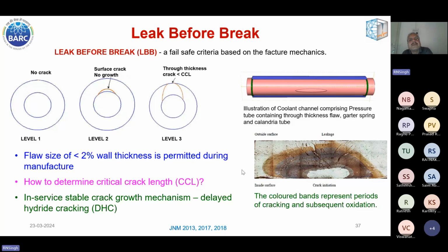No, this crack is just a schematic to show that it is breaching the wall thickness. Usually these DHC cracks are very sharp. It is almost like a sharp planar crack. It is not a volumetric flaw. And for this, I think the actual flaw will have some volumetric nature also, but safety assessment has to be done under the most conservative scenario.